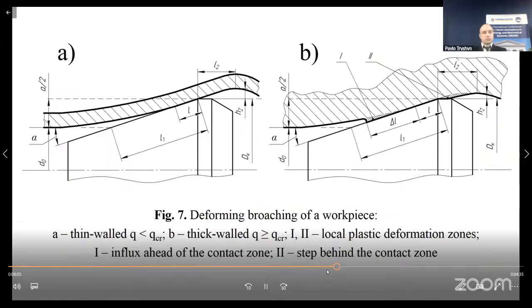The performance study of the deformation zone made it possible to clarify the known scheme of interaction between the tool and workpiece, figure 7a, and to establish the appearance of a local plastic deformation zone, as well as a change in the geometry of the non-contact zone flow of the deformation zone during machining of thick-walled parts. This change is expressed in the flow of the processed materials from the contact zone to the non-contact zone, figure 7b.